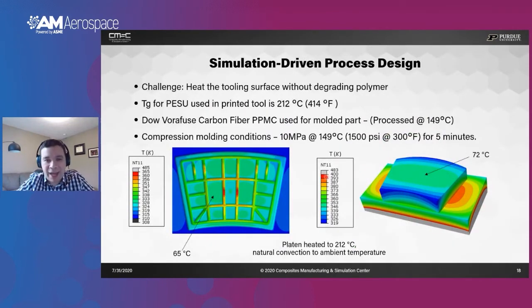Now, the next challenge we have is to heat up the tool to the processing temperature of the material system that we want to compression mold. In this case, even though we have a 25% carbon fiber reinforced polymer, the thermal conductivity is still relatively low since it's governed by the polymer, and therefore it's not as straightforward to reach these processing temperatures as in traditional tools. The material system is PESU, reinforced with 25% by weight of carbon fiber, and it has a Tg of around 212 Celsius.